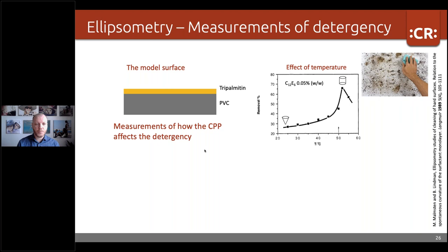So it will turn from a cone shape type of surfactant that easily forms micelles into a more cylindrical shape, where the head group and the tail are more balanced in size. So these will not be good at forming micelles, but this shows you that the optimal cleaning effect you actually achieve when you're close to a critical packing parameter of 1. This is where you have the minimal interfacial tension between water and the oil that you're removing.